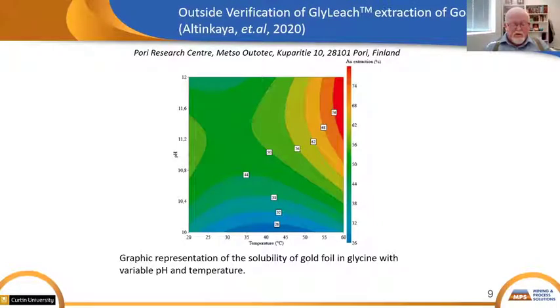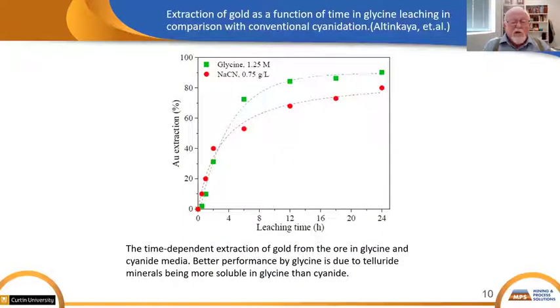Now, what we have here is a graphic depiction of the effect of pH and temperature on the solubility of gold foil in glycine. The vertical axis is pH, the horizontal axis is temperature. And think of it as a contour map showing recovery rather than elevation. And the portion up in the upper right-hand corner is where we have to be when we're trying to leach with this material.